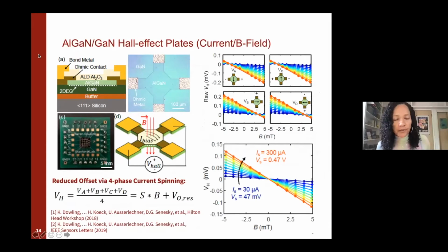So another device that we've developed, another type of transducer, or again, sensing device that can work in concert potentially with a pressure sensor, is a Hall effect plate. So Hall effect is a mechanism that is often used in silicon devices. You carry them around with you in your phone. Oftentimes we use doped junctions to make a Hall effect. Basically what's happening is that in the presence of a magnetic field, if I apply a bias to one set of electrodes, due to the Lorentz force, we get bending of the electrons, and we can measure that sensitivity with a secondary set of electrodes to measure the Hall voltage.